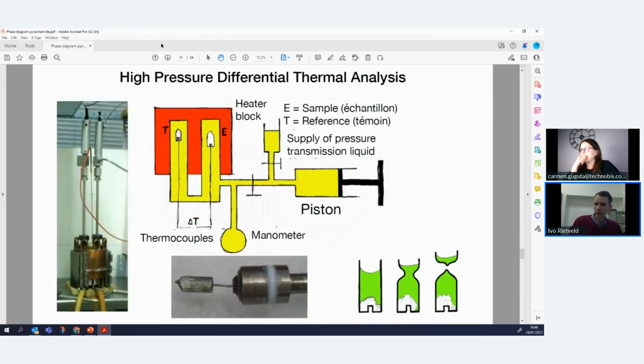This is just to show you how it works. This is a high pressure differential thermal analysis. It's like a DSC, but a bit more simple. You measure temperature differences of a sample and a reference. Here, the reference is the T, but that doesn't matter. And you put it basically under pressure with a liquid, and that you can control depending on the temperature. You can calculate pressure and measure the temperature also, and in that way you can work out the phase behavior under pressure. This system can go up to about 300 megapascal. There is another system in Barcelona that can also go up to 500 megapascal. The trouble is, combining heating and pressure is often a little bit of a tricky thing. We can go to the next slide.